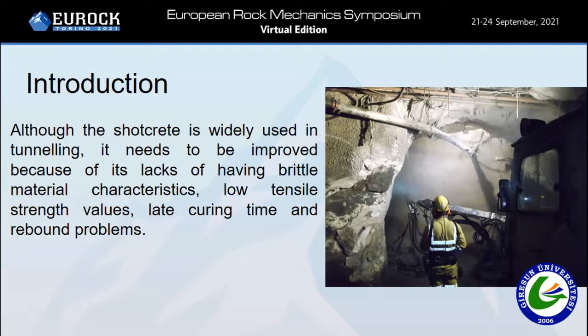Although the shotcrete has become a worldwide standard tunnel liner, it needs to be improved because of its lack of brittle material characteristics, low tensile strength values, late curing time, and rebound problems. To overcome the problems of shotcrete liners, different chemical additives and reinforcements are used in shotcrete mixes. However, the shotcrete liners still have many issues needing significant improvements. For instance, shotcrete liners show early cracking while being deformed despite the use of different additives.